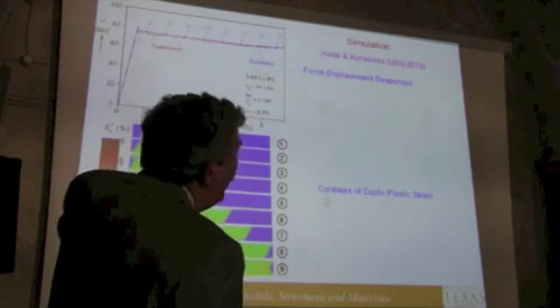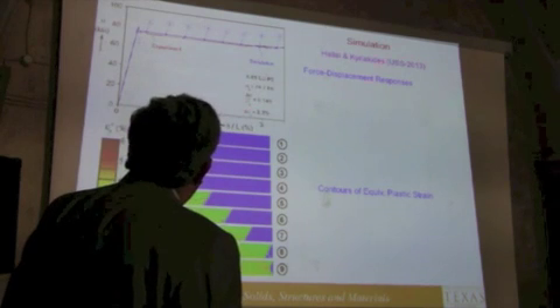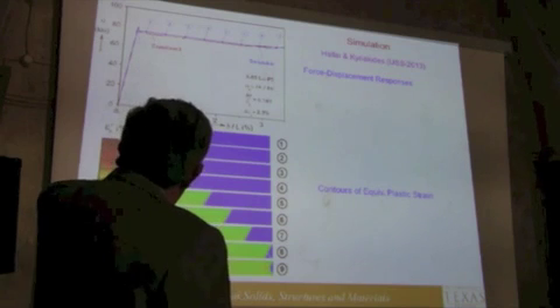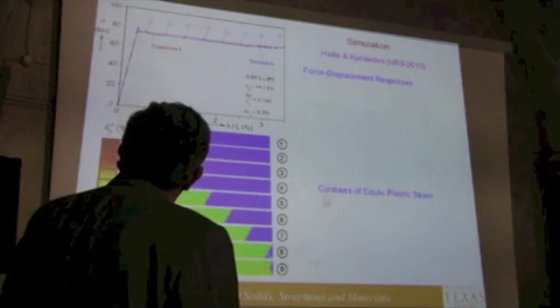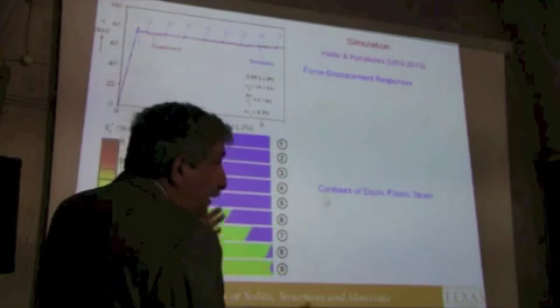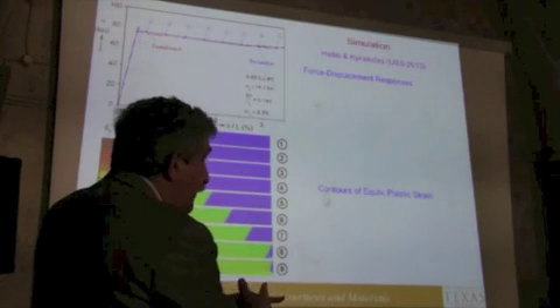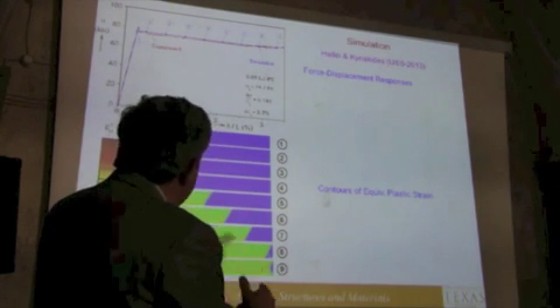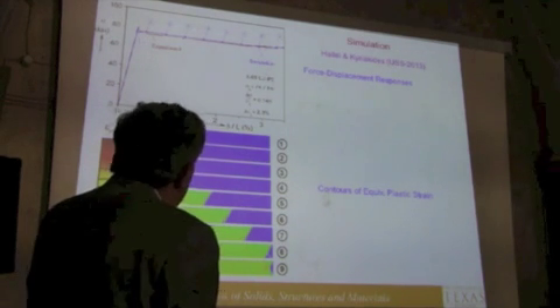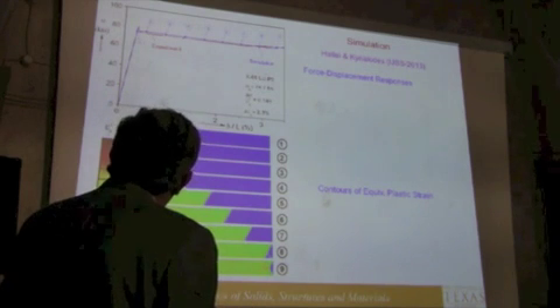So this now is a finite element model. It's the newer version of the same calculation of my later PhD student. But you can see that with just that, you get the initiation. It's a band with a particular orientation. The orientation is plus minus 55 degrees. For you guys that are theoretical, this is known as the Hill angle, and there are two characteristics, and it's along one of those characteristics, and then it propagates, as you can see.